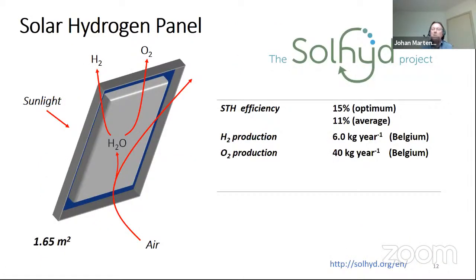And here are some figures. So we reach 15% efficiency at optimum conditions. So with perfect orientation, with the best combination of relative humidity, because in our case, it's not only the sunshine that matters, but also the relative humidity. It's a combination of the two. So the average, if you put it outside in Belgium, over a year time, all the seasons, winter, summer, autumn, spring, we get 11% average. So that means in Belgium, 6 kilograms of hydrogen produced for one panel, which measures 1.65 square meters. And of course, we make more oxygen because the oxygen atom is, of course, heavier than the hydrogen atom. You are all chemists. So that's simple.